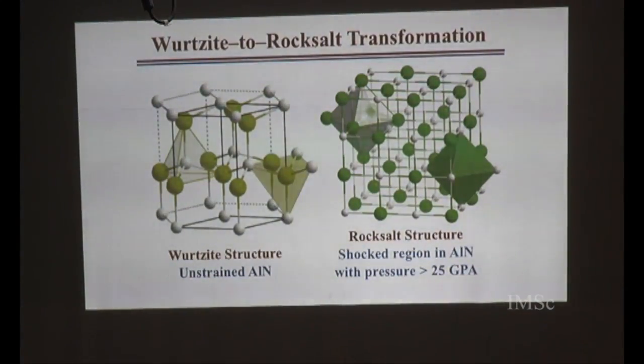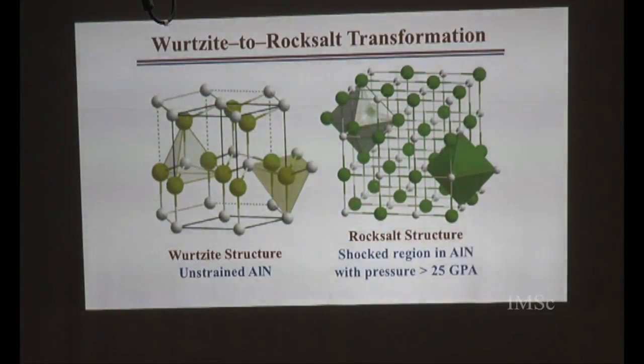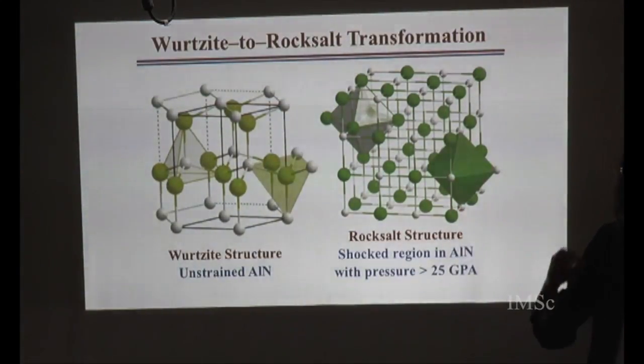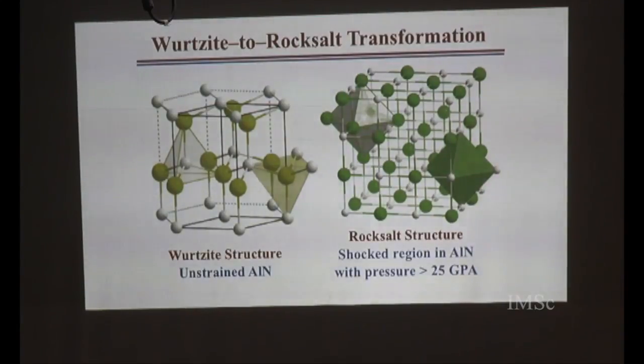So the thing is, aluminum nitride crystal, when you start with an unstrained system, it is in the Wurtzite structure. In the Wurtzite structure, if you look at an aluminum atom, it has four-fold coordination. And under compression, when the pressure is more than 25 GPa, it undergoes a structural phase transformation, and the structure changes from this to rock salt structure. Rock salt structure is a sodium chloride kind of structure, in which case an aluminum has 6 nearest neighbors, okay? So that's the transformation. What you saw in the movie was the stress wave was going, it produced compression exceeding 25 GPa, and there was a structural transformation happening in the system as the stress wave was going.